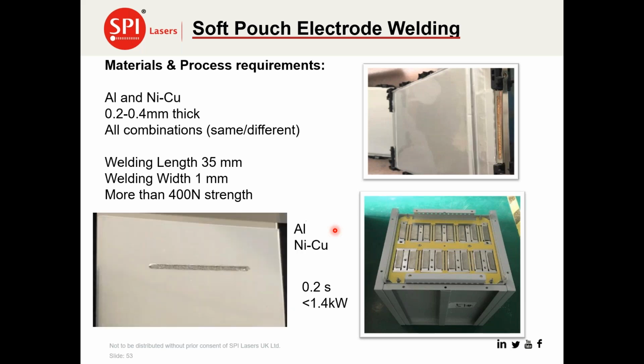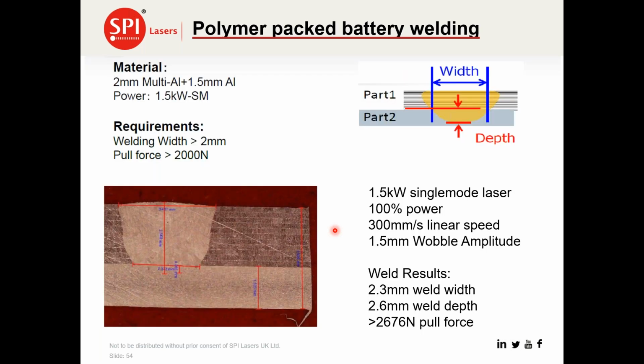There's aluminium to aluminium, aluminium to nickel plated copper. So all of the different combinations that are commonly looked at by battery manufacturers are achievable using these oscillation techniques with single mode lasers.